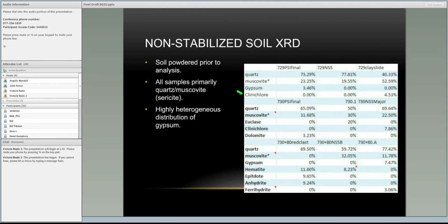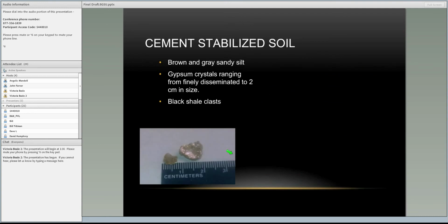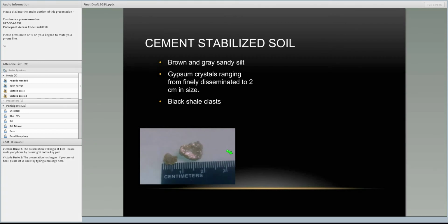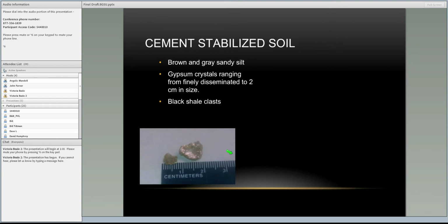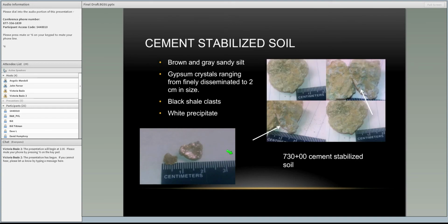Then we looked at the cement stabilized soil, and it looks very similar to the non-stabilized soil. Not as much black shale in the cement stabilized soil. And what we did notice that was different between these two soils is there's a lot of white precipitate in the stabilized soil. And so we really focused on these areas because they stood out. And also in reading literature, we thought that the white precipitate could be gypsum or maybe even ettringite. So we really started out focusing on those areas.